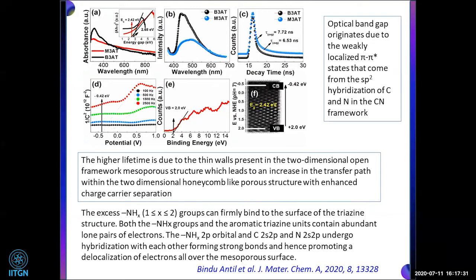And you can see that the average lifetime of the charge carriers in the nano sample is higher than the bulk sample. And you can see the photoluminescence also. In the case of the nanosheets it is lower because there is photoluminescence quenching, because the electrons are not recombining with the holes. And as I described earlier, the excess amine group, NH2 group, firmly binds to the surface of the triazine ring, and both amine groups and aromatic groups give abundant electrons for the photocatalytic hydrogen evolution.